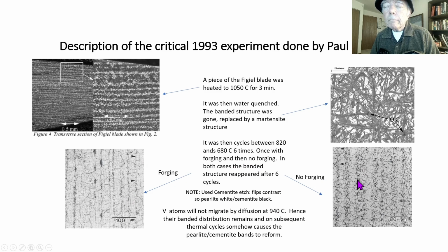The bands come back magically. This uses cementite etch, so the bands look black on a white matrix. What's going on here, we think? Well, the vanadium atoms do not migrate by diffusion at 940. Hence, their banded distribution remains. And on subsequent thermal cycles, somehow those bands of vanadium cause the pearlite cementite bands to form.